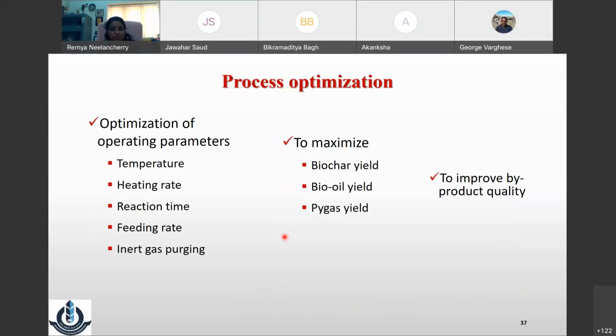Now, how to do the process optimization? This is more or less the same as that of the conventional pyrolysis process. Once the feedstock is fixed, once the feedstock to susceptor or microwave absorber ratio is fixed, again you can play with your process optimization, that is, optimizing the operating parameters. Of course, what should be the temperature, at what heating rate, what reaction time, or what should be the feeding rate, inert gas purging, and so on, to tune your pyrolysis end product.